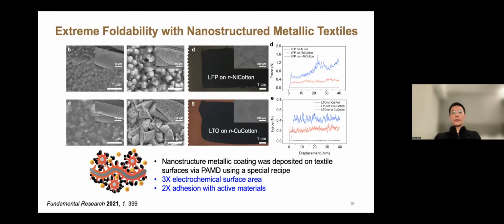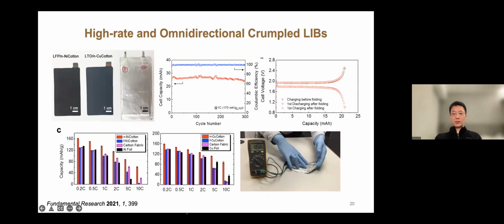So later on, we want to challenge a little bit of the flexibility, all right? So what we find out is that lithium metal, indeed, you can't really fold it in a certain way. You can fold it a couple of tens of times, and then the cell probably will decay rapidly. But then if you just use commercial materials, and then you can adjust the slurries, and most importantly, if we can make some nanostructures on the metal deposition, in our case, we make some nano needle-like structures. You can improve the electrochemical surface area. You can also increase significantly the adhesion between the active materials and the surface and the current collector, so that we can push the flexibility to the extreme, right?